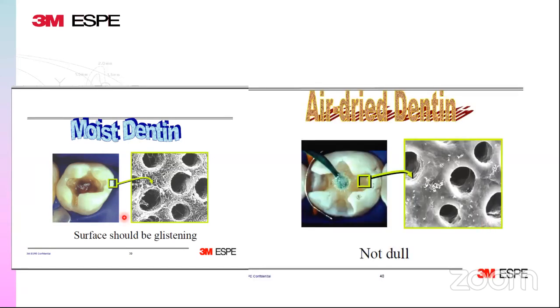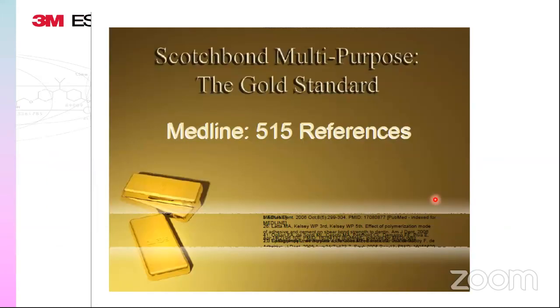Now, this is a huge difference between your moist dentine and dry dentine, which was causing the problem of post-op sensitivity. That is why I've been saying that this is a technique sensitive method, especially if you're looking for total etch. If you over dry or under dry, you will not get this kind of picture. You'll get this kind of picture, and of course that leads to a weaker bond and higher post-op sensitivity. So what do we do?